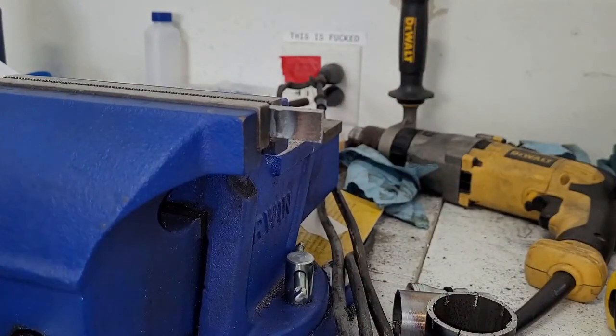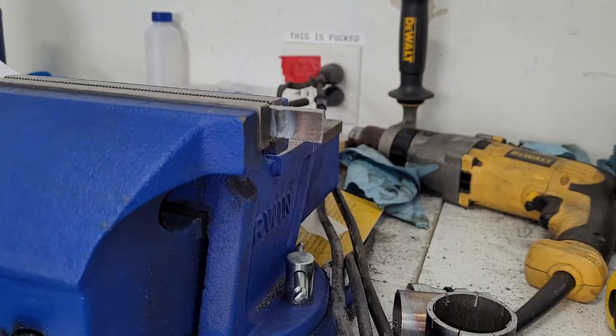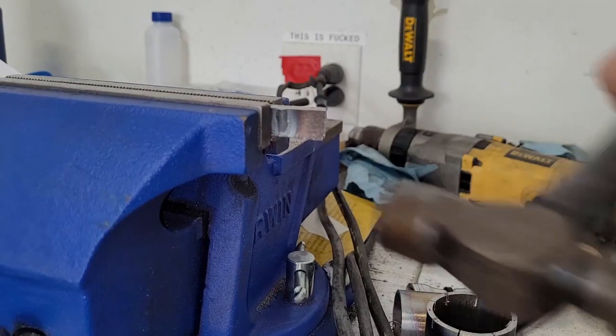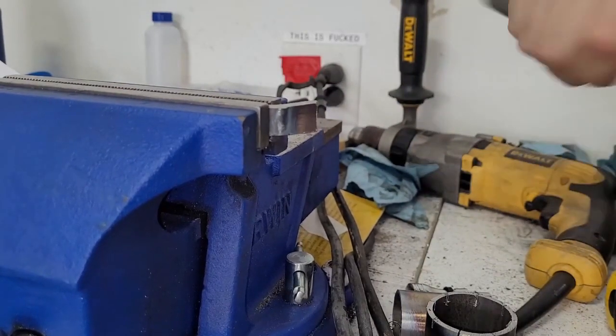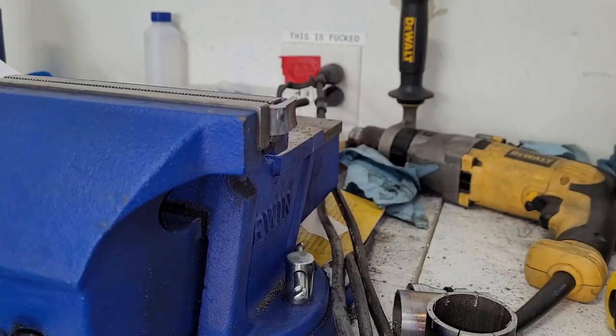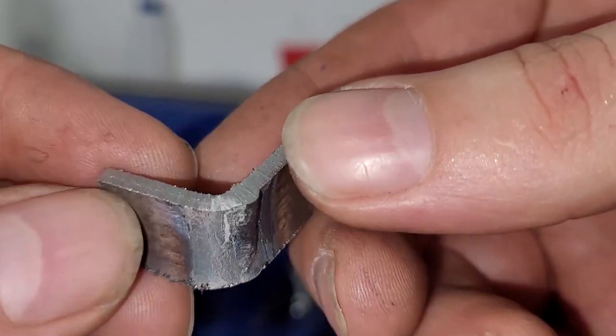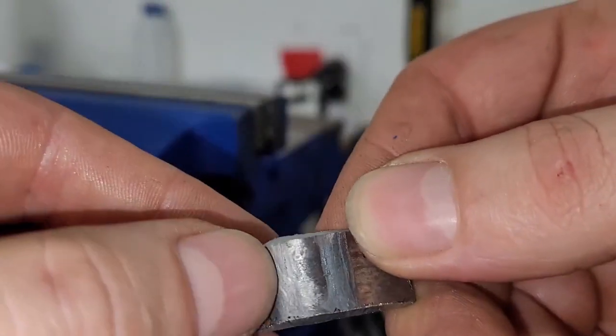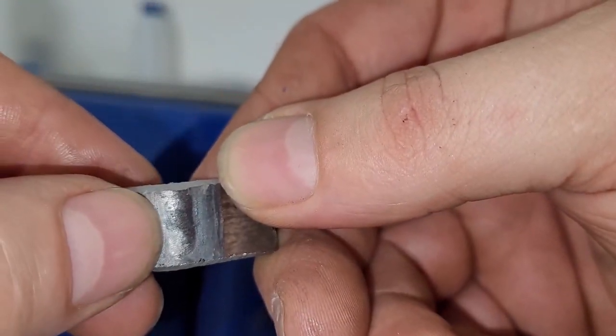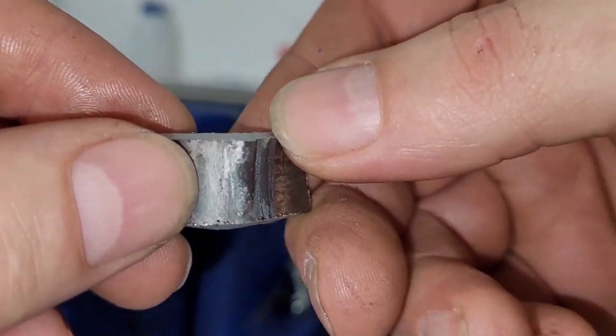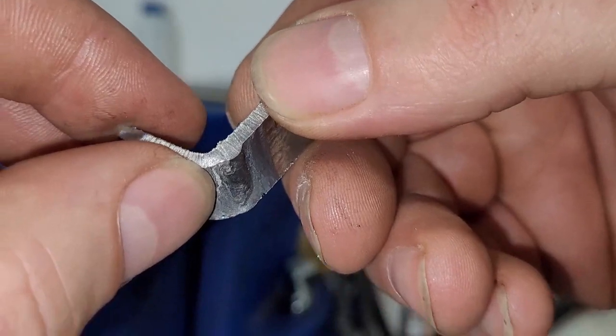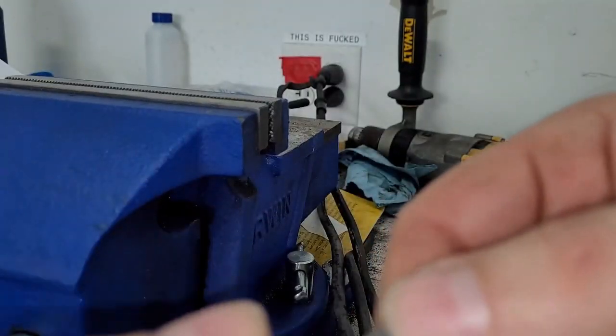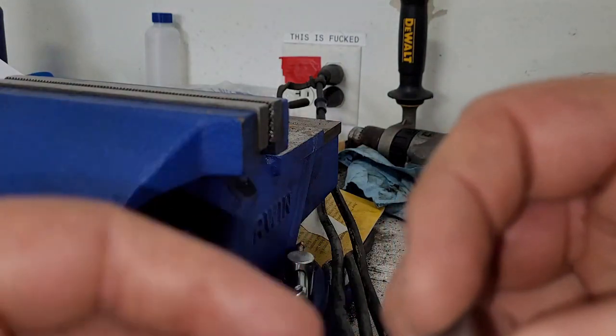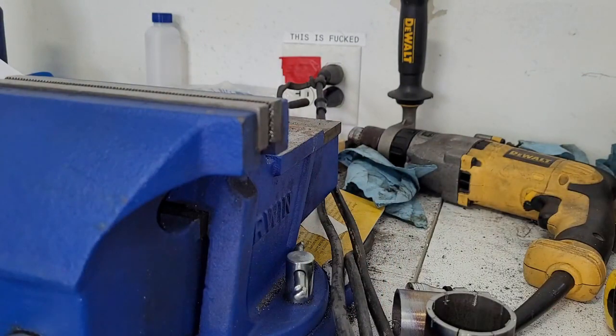Here's sample number 8 from the first weld. This one's actually got a decent weld, so if it cracks, it's probably going to be down here at the bottom. Nope, cracked at the top. And it cracked in the heat affected zone, not in the weld itself, but in the area immediately next to the weld. I don't know how good that shows up on camera, but there's a crack near my fingernail there. But, I mean, we did bend this 90 degrees pretty hard. Okay, now let's try the next group.